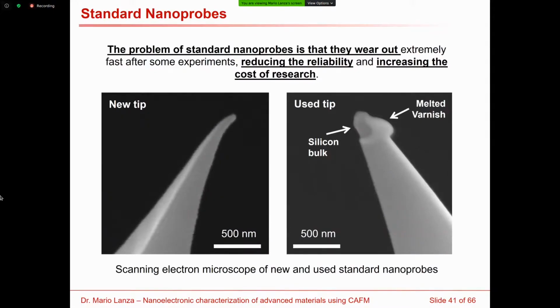The most important problem in conductive AFM science is that we use metal-coated silicon tips that are very sharp. And after you do some measurements, due to the mechanical frictions or due to the high currents, which increase the local temperature, you can damage this metallic varnish. Then your tip is not conductive anymore, and you need to use a new one. These tips can degrade really fast, depending on the measurement that you do, and they are expensive. So you always want to preserve the tip for two reasons. First, to reduce the cost of your research, and second, to ensure the reliability of the data that you are collecting. Because if the tip has degraded between the first and the last measurement, then all you have in between cannot be considered.